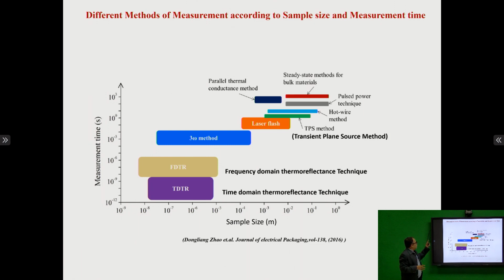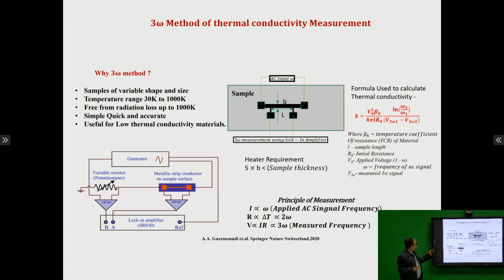So we developed in our lab a 3 omega technique with which we measure the thermal conductivity of materials. What is this setup? We create a line heater on the sample. When there's a line heater, you need to give a very small current or heat, so the radiation losses get minimized and the error is very low. That is the 3 omega method.